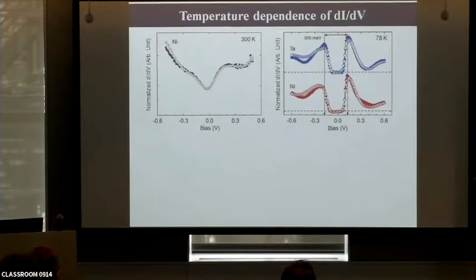However, considering some broadening, it is more natural to assign the gap size as the peak-to-peak distance. So here, the peak-to-peak distance is 300 meV, which is the genuine energy gap in the excitonic insulator.